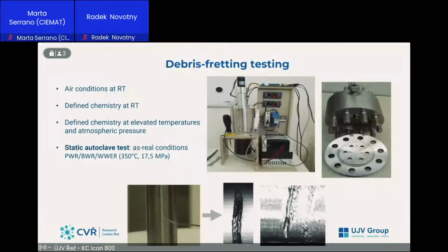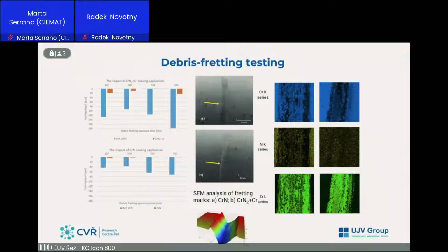Going to the very perspective method of debris fretting testing, which is performed by our fuel group. Debris fretting tests we can perform in air at room temperature, in wet conditions with defined chemistry, as well as at elevated temperatures, and we can also simulate real conditions in the autoclave: PWR, BWR, and VVER conditions. Here are some results from the debris fretting tests where we compared two types of ATF claddings, and the fretting depth of different coatings is visible, supported by the microstructure where we can compare the results on the surface damage.